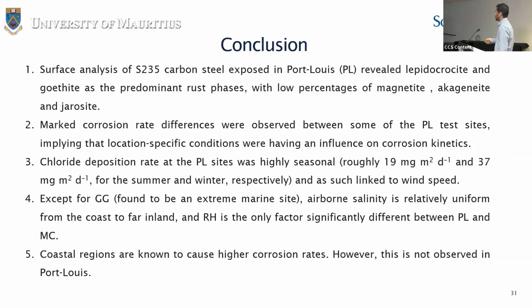The chloride deposition rate at Port-Louis is highly seasonal, and as such, it is linked to wind speed. That is, the weather conditions influence corrosion rate in this region. Except for GG, which is an extreme marine site, airborne salinity is more or less uniform from the coast to far inland. And the only factor significantly different between Port-Louis and MC is relative humidity. Relative humidity is higher at MC, the mid-island atmosphere, and that site has a higher corrosivity category than Port-Louis, which is a marine region. Finally, coastal regions are known for high corrosion rates. However, this is not observed in Port-Louis.